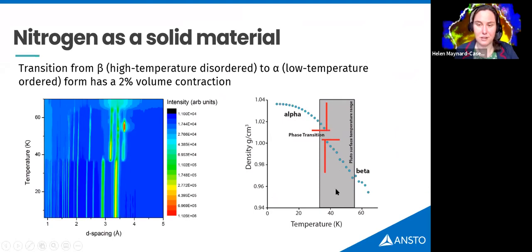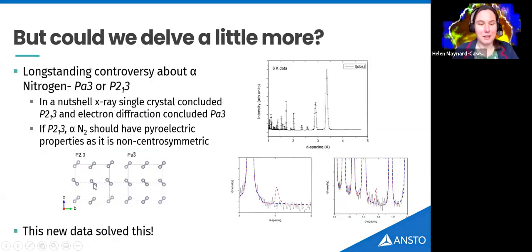But nitrogen is perhaps a little bit more interesting because it does have a phase transition over the seasonal variation of Pluto. And in this work, we were the first to classify that density change. And you can see we go from the disordered high temperature beta form to an ordered alpha form as we cool down. And again, you'd have thought by now we should know what the crystal structures of the elements are. No. It turned out when I collected this data, and I was quite surprised at how beautiful it was, that there was a long-standing controversy on the crystal structure.